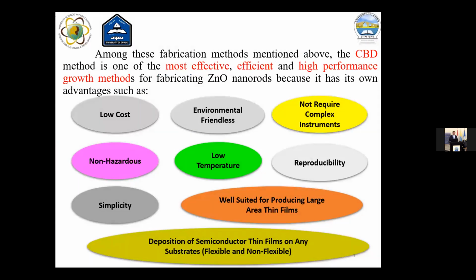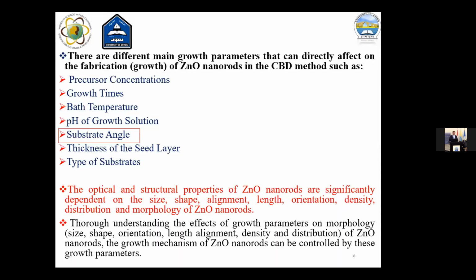In this research, I focus on the chemical bath deposition method because it is one of the most effective, efficient, high-performance methods, with advantages such as low cost, low temperature, environmental friendliness, no need for complex instruments, simplicity, non-hazard, and the ability to deposit semiconductor thin films on any substrate, flexible or not flexible. Also, the nanostructure can be controlled by different main parameters that directly affect its properties, such as precursor concentration, growth time, bath temperature, pH of the growth solution, substrate angle, thickness of the seed layer, types of substrate, and other parameters.